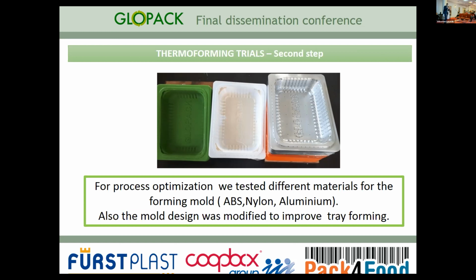After that we switched to nylon, which was a little more resistant to the heat. But in the end, we switched to aluminum because this was the only material that was able to give us a good thermoformability of the tray without any degradation of the mold. Also, we changed something about the machine to improve the stretching of the material, because the material is not so easy to stretch. So we decided to make some modifications to improve that.